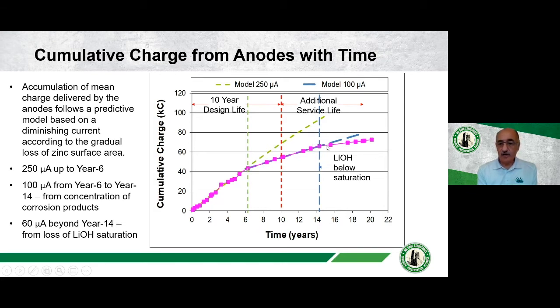We are pretty certain that we know what happened at this stage, and that's because we were adding lithium hydroxide just enough for a 10-year life of the anode. That was the original design. It lasted a bit longer, but eventually it was going to run out. So here we've now got non-saturated lithium hydroxide, i.e. the pH is beginning to drop, and as I've shown earlier, the activity of the zinc depends on the pH of the electrolyte. So we measured the pH of the electrolyte from the anodes that we removed, and that was pH 13.9, so it dropped from 14.6. Therefore, that reduction in current output was related to the consumption of the lithium hydroxide.